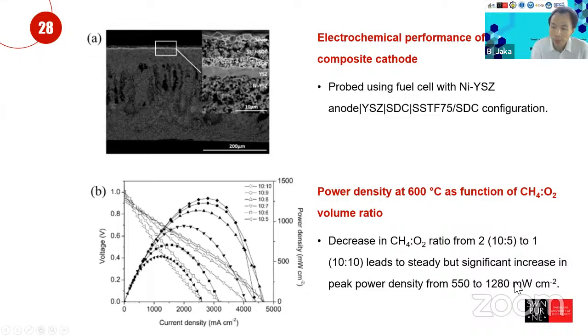We managed to get 550 to 1280 milliwatt per centimeter square as we play with the CH4 to oxygen ratios in here. So this solid oxide fuel cell is a bit special in that we don't operate it using hydrogen, but we use methane. Obviously it would be more expensive to fuel a fuel cell using hydrogen than using methane, because methane is more abundantly available. Whereas hydrogen needs to be produced by electricity or using steam methane reforming of methane.